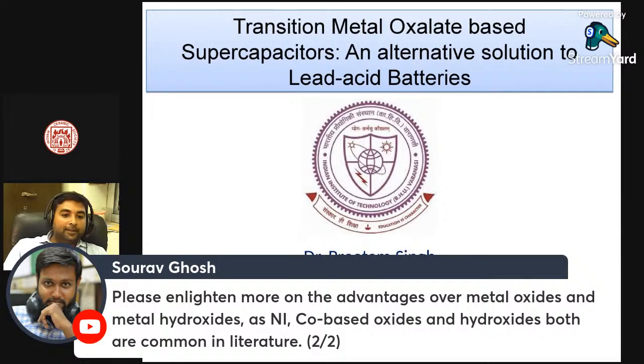So here we are not getting the conversion of nickel oxalate into nickel hydroxide. See, it's the intercalation of the hydroxide ion into the nickel oxalate framework. So you may think that the new compound is a hydroxycarbonate, and when you discharge it, then the hydroxide is gone and you are able to retain nickel oxalate. So see, the framework remained stable, and that's why it will give very stable performance. To avoid the structure collapse, the framework, even from the oxalate or even a bigger framework, can be utilized. However, we are finding that this carboxylate framework is sufficient to give the stability to the electrode.